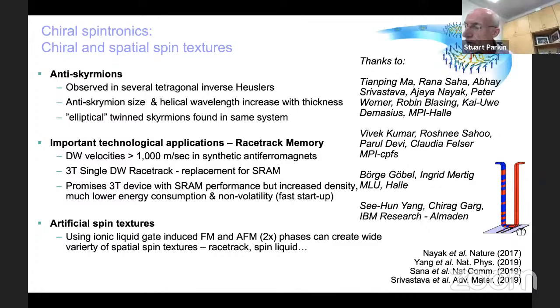So a wide variety of material combinations have been considered using cobalt and nickel and various elements. And even for the same, let's say, heavy metal like platinum or tungsten, depending upon the magnetic layer, whether it's nickel or cobalt, you could change the sign of the Dzyaloshinskii-Moriya interaction. So I think there's no simple answer, but as you said, it's obviously due to electronic matching within the two layers, and I don't think it's a double layer, but it's simply the electronic structure effects and how they are implemented. And so, of course, you can tune this by changing the individual elements, or by forming binary or ternary alloys. And you could use this, of course. I think maybe your question is, in the end, not only can you change the sign, but more importantly, you can change the strength. And you can tune the strength significantly by alloying, just as you said, change band filling effects.